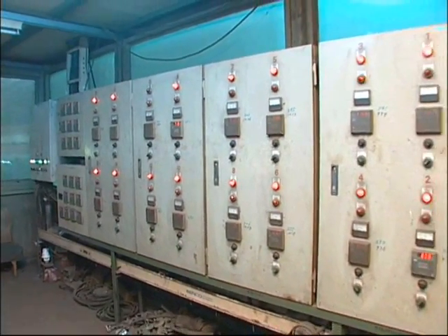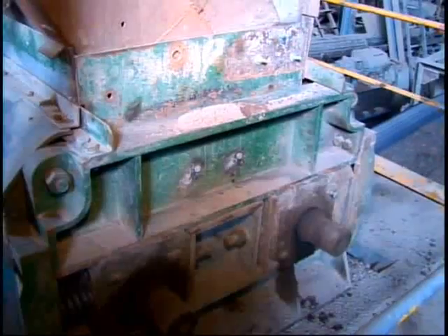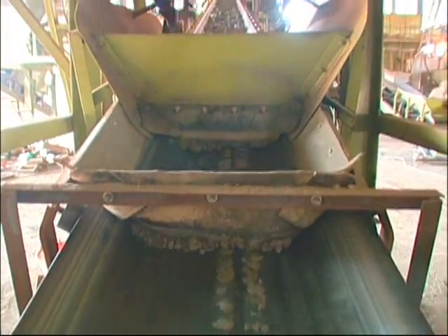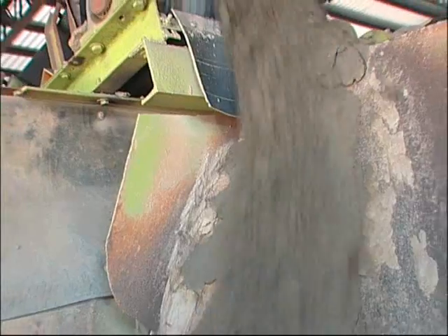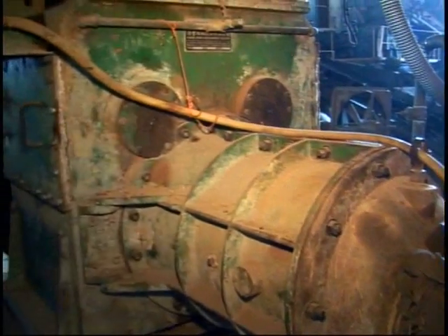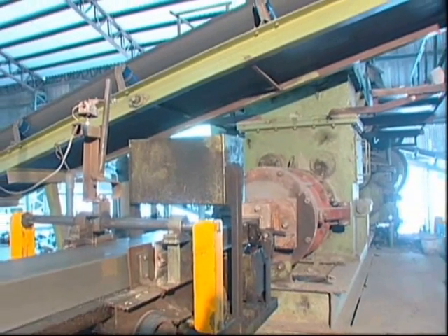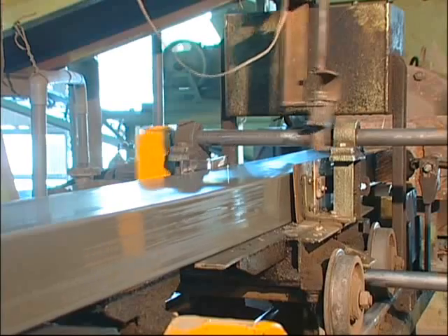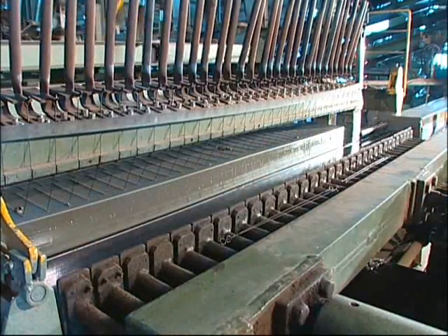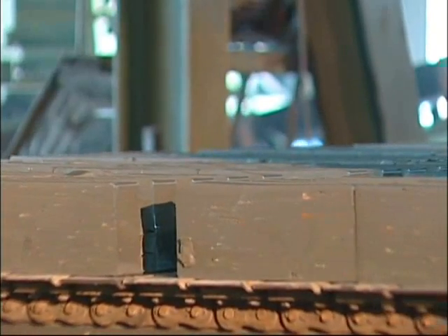The manufacturing of an automated brick kiln starts from feeding the raw clay into the feeder for coarse crushing, medium crushing, and fine crushing, which becomes the raw material that will be put into the blender and mixed with water, and then vacuum extruded by the brick making machine in a 100 mm by 220 mm continuous strip. It will be cut into approximately a 55 by 100 by 220 mm size.